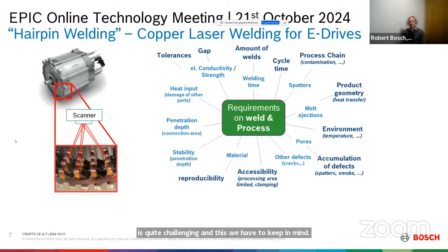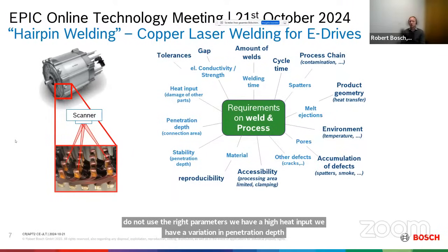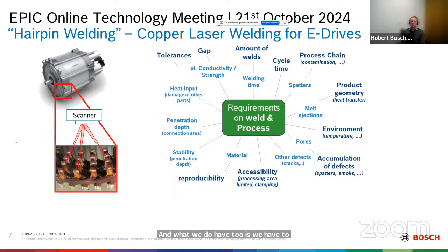And another example is if we weld copper. Copper is quite challenging in laser welding. And we do have to weld copper if we're talking about production of e-drives, so production of hairpins, for example, or stators. We have these light blue requirements here. We have spatter formation, melt ejection, pores if you do not use the right parameters. We have a high heat input, a variation in penetration depth. And what we also have to consider is the whole process chain, so the requirements from the process chain: the product geometry, the environment, accumulation of defects, tolerances, and so on.